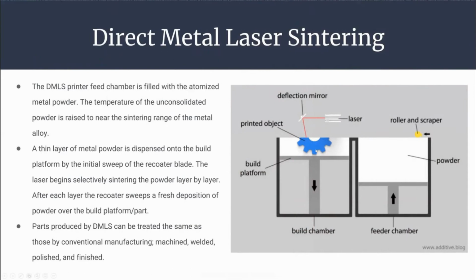So just going a little bit into direct metal laser sintering, if people are not familiar. The printer feed chamber, you can see in the illustration here on the right, is essentially a volume with metallic powder, this atomized metallic powder. And this can be a variety of things. It can be aluminum, it could be titanium. In this case, we used a steel. What happens is the powder is pushed up from the feeding chamber and swept across the build platform in an even deposition layer. Then it's hit with the laser from the printer, and that fuses the metal powder into the shape you desire, to the CAD design that you've uploaded into the printer. With each successive layer, the powder bed will be raised, the build chamber will be lowered, and the roller, scraper, or recoater will deposit a new layer of the powder over the build platform.